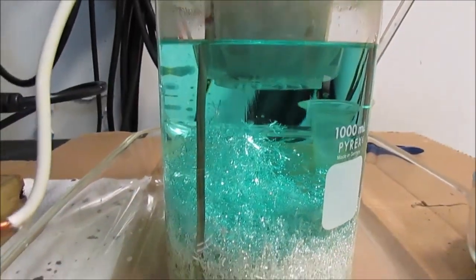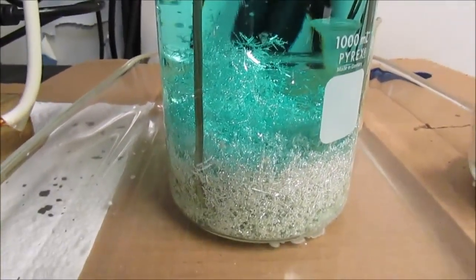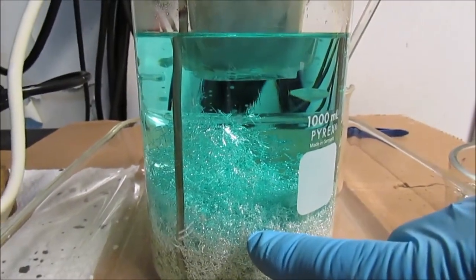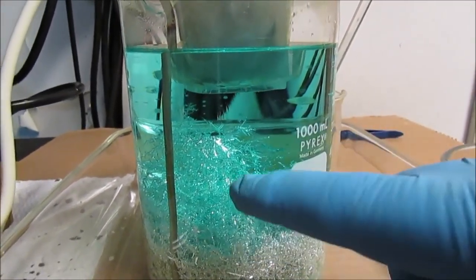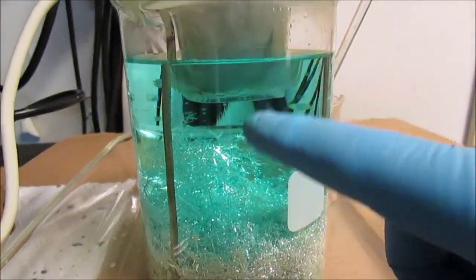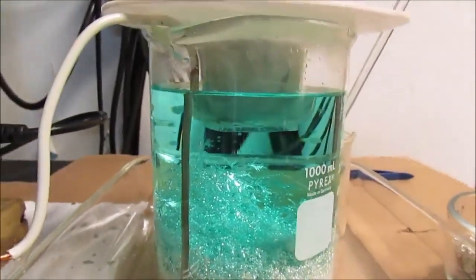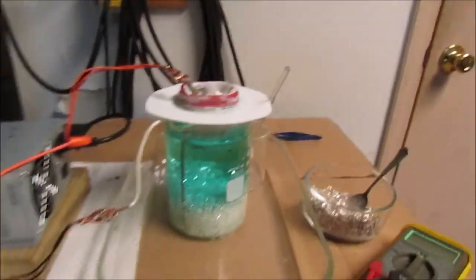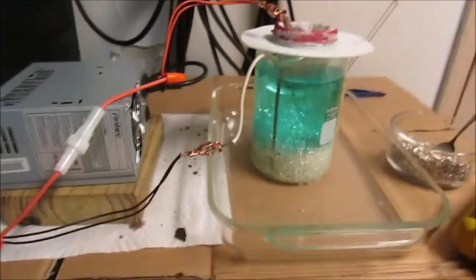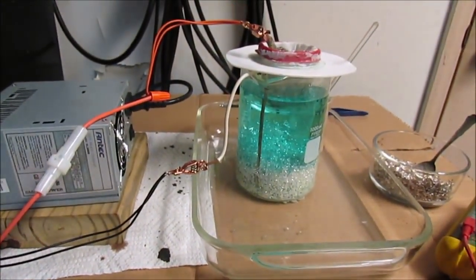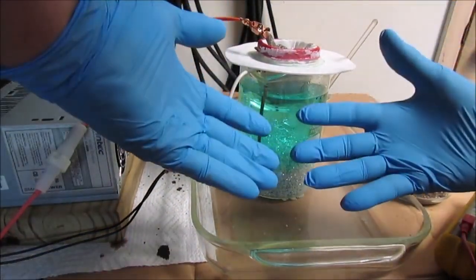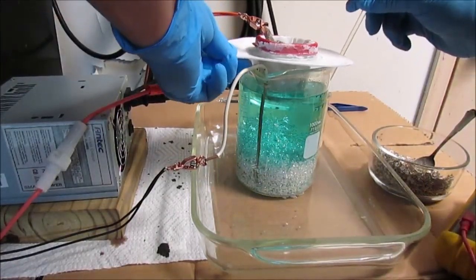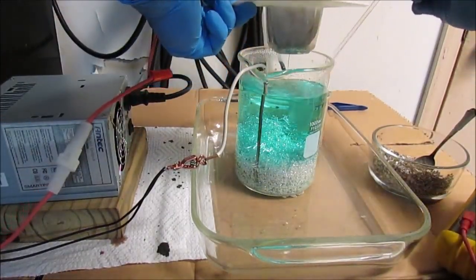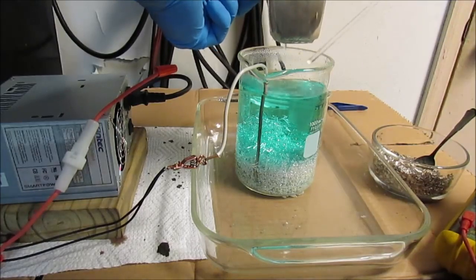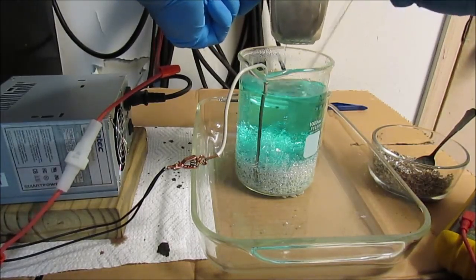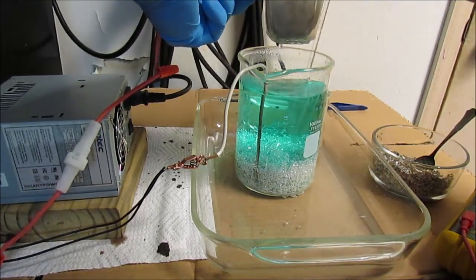This is day 5. The silver cell is starting to get kind of, the levels increasing here, so it doesn't take long for these crystals to grow up near the anode basket. It's only been a half an hour since the last time I pushed them down. So I'm going to go ahead and push these down again. You got to make sure and wear gloves. You don't have to have nitrile gloves, but get something on your hands to protect them from this electrolyte. It's made out of silver nitrate and it will stain your hands black.